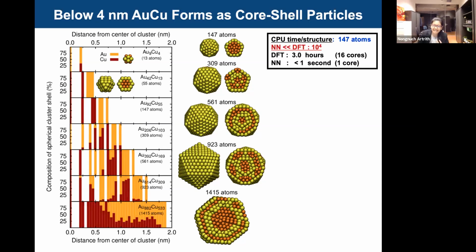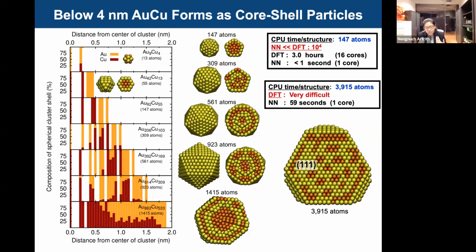Of course, this work was done in 2014. I know that now you have much better computers, but I just keep this consistent with my time and my year. But with the neural potential that we developed, it takes just 1 second on my laptop. It's just 1 core, as you can see here. And realistic nanoparticles or clusters of around 4,000 atoms with DFT is very, very difficult. With the neural potential that we have, it takes about 1 minute to predict such compositions.